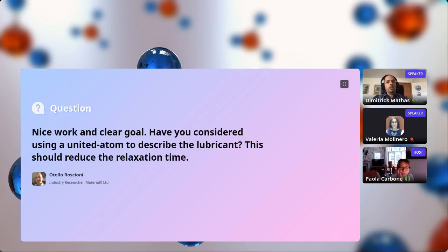I was asking because I wonder if in your non-equilibrium MD you see any crystallization when you shear it quite highly. I believe I've seen some graphs from other papers that suggest crystallization, and I think crystallization also has an influence on the viscosity. This can be seen from viscosity, but in our case, we didn't see crystallization, and we had a shear thinning region at the higher shear rates.